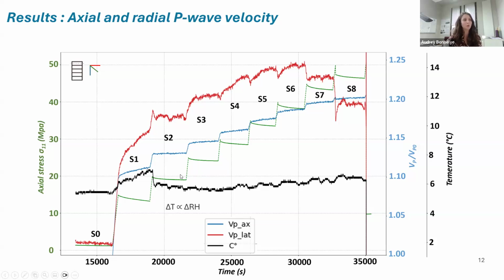What we see is mostly compaction, because we see an increase of the P-wave velocities all along the loading of our sample. But toward the end of the experiment, close to failure, we have a different evolution of our P-wave velocities. During our steps, we have some decrease of the velocity linked to the damage, but we also observe some recovery that is actually linked to the relaxation steps.